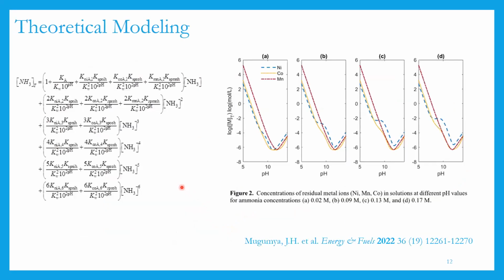I'll speak briefly about the theoretical model that was used. Basically, you start with equilibrium constants, and then you solve, and finally you get an equation, a polynomial, which you can solve in MATLAB. When you input different pH values for a specific ammonia concentration, you get a plot which shows you how much metal ion is still in the solution at different pH values.